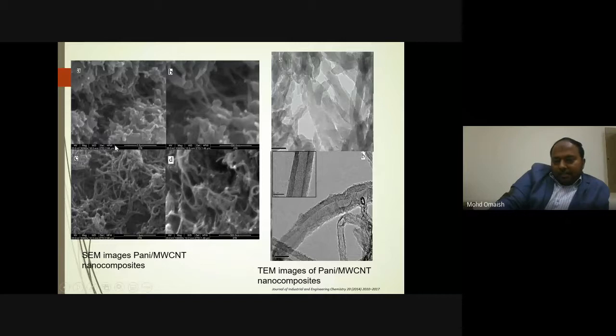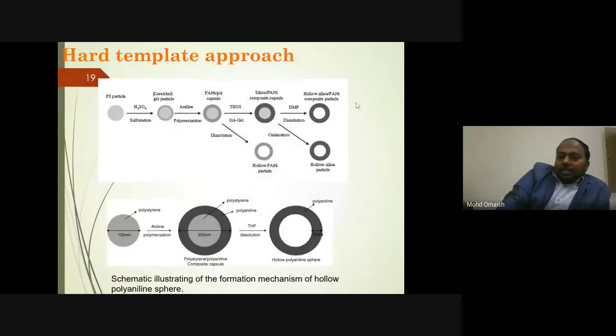In the case of polyaniline CNT, we got a very good coating of polyaniline on CNT and pure elongated polyaniline fiber, while in the other case the fibers were very short. The other is the hard template growth approach, in which we use some hard particle like polystyrene or silica to get a particular morphology like core-shell. Here we used polystyrene, and the authors coated polyaniline on it, and after removal of the polystyrene core, we can get a hollow polyaniline particle.